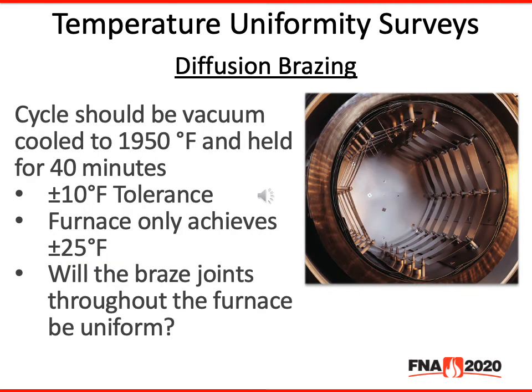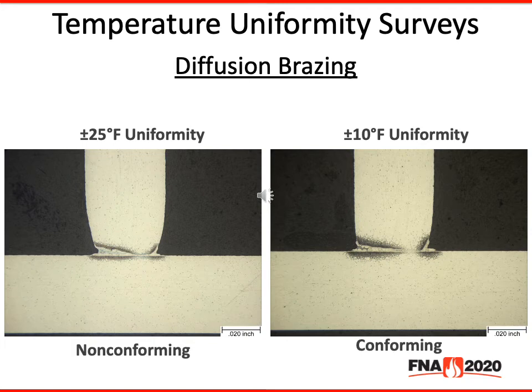Once the high temperature braze cycle is completed, the part should be vacuum cooled to 1950 and held for 40 minutes. It should have a plus or minus 10 tolerance. Hypothetically, let's state that the furnace used could only achieve a plus or minus 25 tolerance. Will the braze joints throughout the furnace be uniform? As you can see, the braze joints do look very different. On the left is a braze joint subjected to the plus or minus 25 uniformity. On the right is a braze joint subjected to the plus or minus 10 degree uniformity.